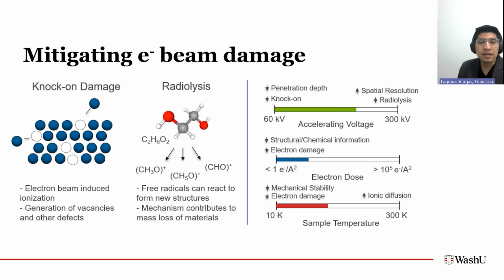And each one of these types of damages is more prominent in a different part of the h-MXene. So for example, knock-on damage occurs when the electron beam comes in and ionizes atoms in the material. And this is expected to occur more in the Ti3C2 lattice, in the h-MXene part of it. However, radiolysis occurs when you start breaking bonds between molecules, and this is expected to happen more severely in the organic surface groups of these hybrid materials. The challenge is kind of finding a sweet spot where you can mitigate both of these damages.